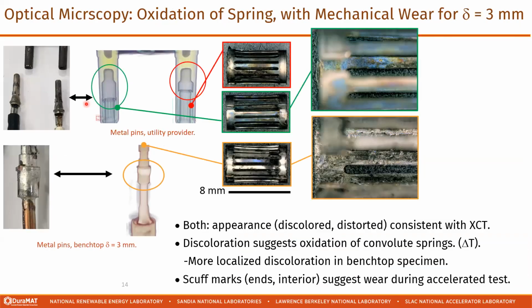So when we apply that sequence here, milling away the plastic, there's an obvious discoloration from the field components. This is the one with the asymmetry. And then when we extract the convolute springs, these are discolored, right? So that suggests that we've been at some sort of elevated temperature enabling an oxidation. And relative to the field sample, this is the sample that's been through the accelerated testing.